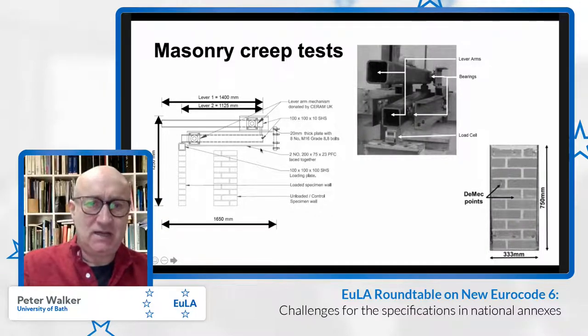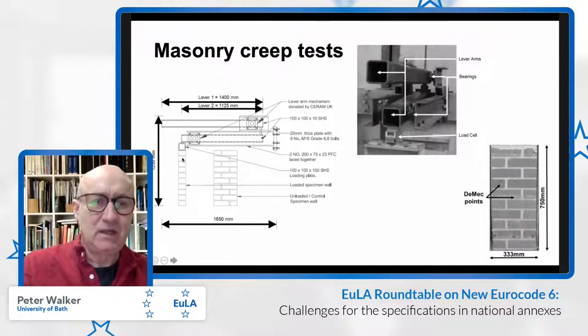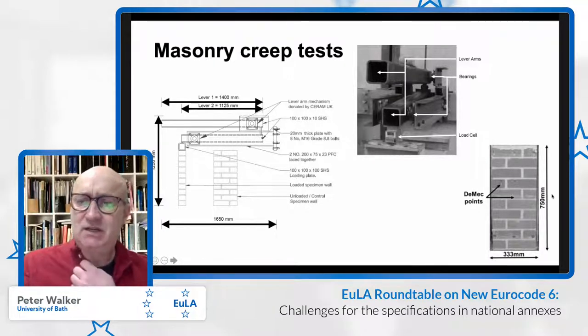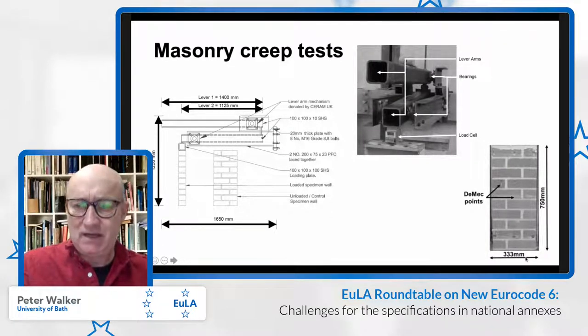In the arrangement in this diagram, the lever arm was fitted back to our strong wall in the lab, and then a mass was hung from the free end here and applied the load to the specimen. For each loaded wall specimen, there was an unloaded control specimen, an identical specimen as well. The walls were the same as presented earlier, 750 millimeters nominally high and 333 millimeters wide.